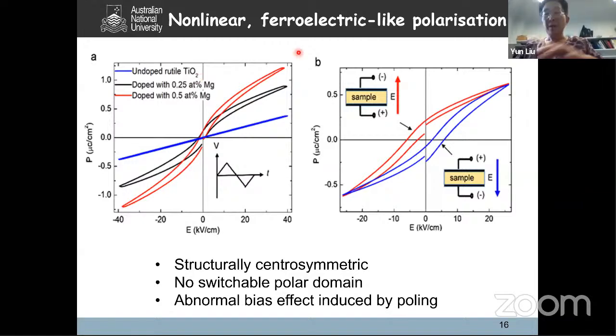Okay. So that's how difficult to dope ions can be accommodated by extrinsic ions you deliberately introduce, so they are correlated to each other to form a defect cluster. Or you can significantly, locally, break this structure to create new defect cluster regions, and as a result affect the property. Okay, so that's one strategy.